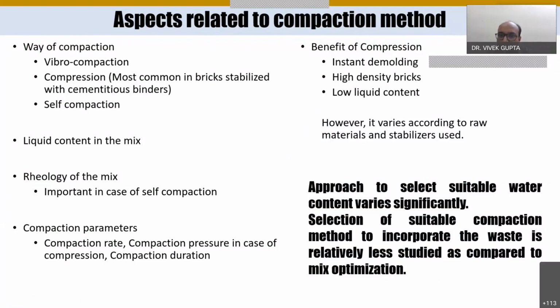Then what is the benefit of compression? It gives instant demolding, high density of the bricks, and a low liquid content is required. However, it varies according to raw material. I have already explained that. Then the approach to select the suitable water content varies significantly in the literature, which we have worked on. I have explained in the previous slides. And the selection of a suitable compaction method to incorporate the waste is relatively less studied as compared to mix optimization.